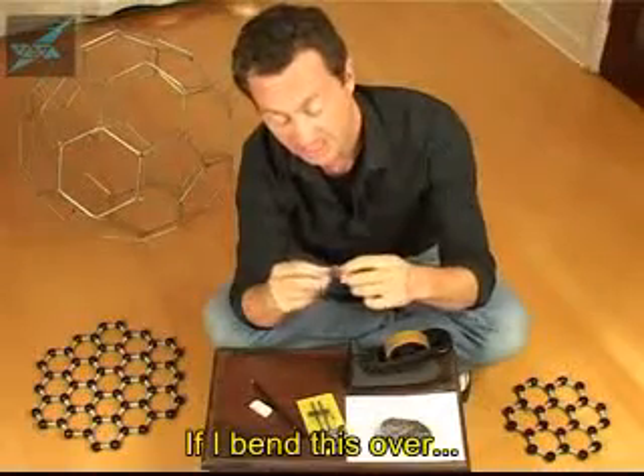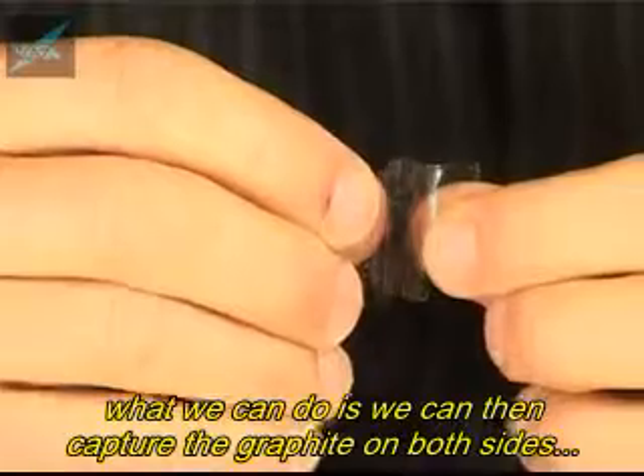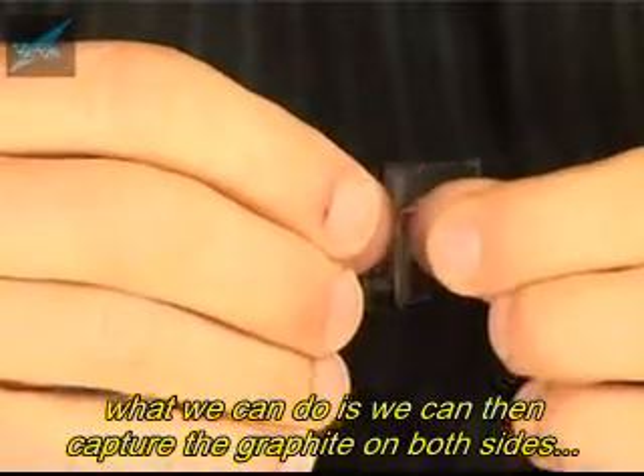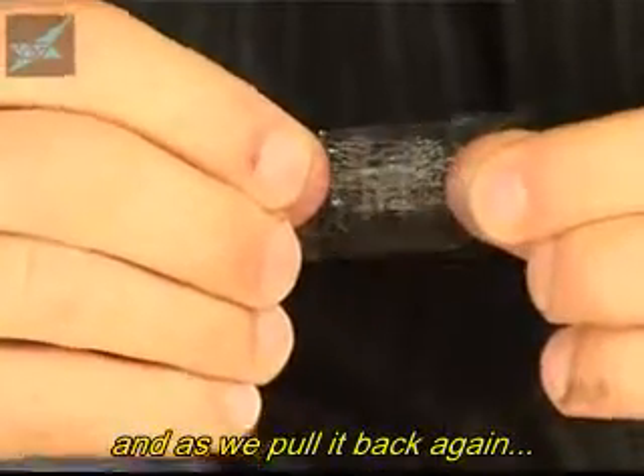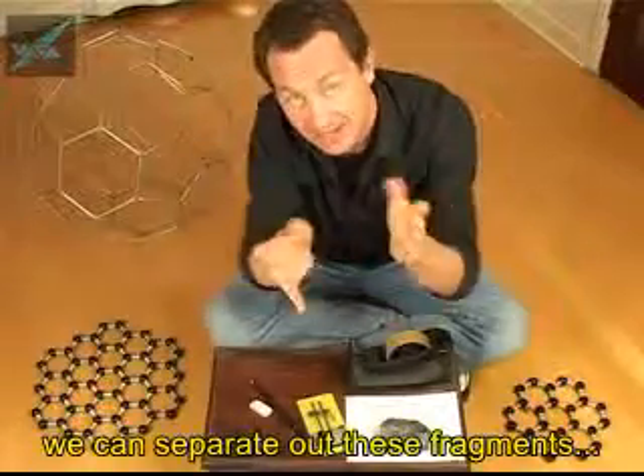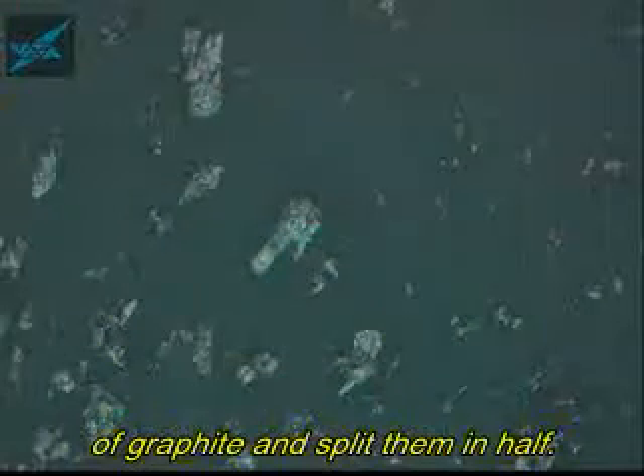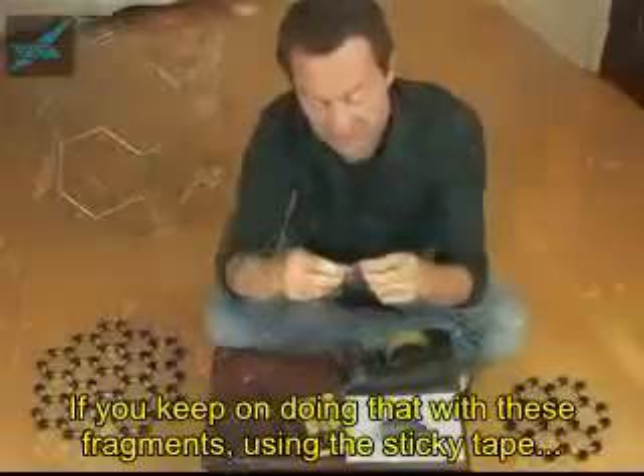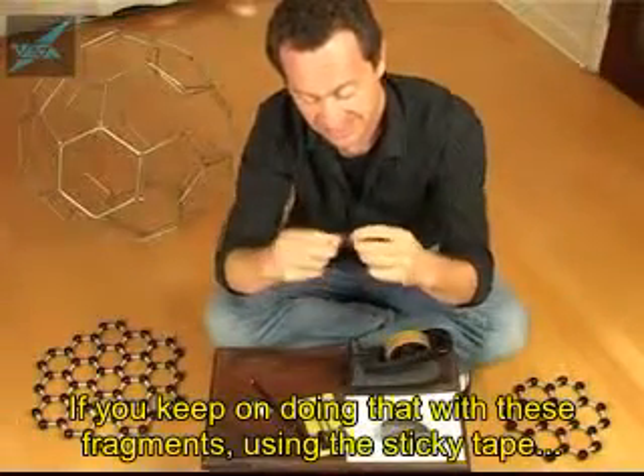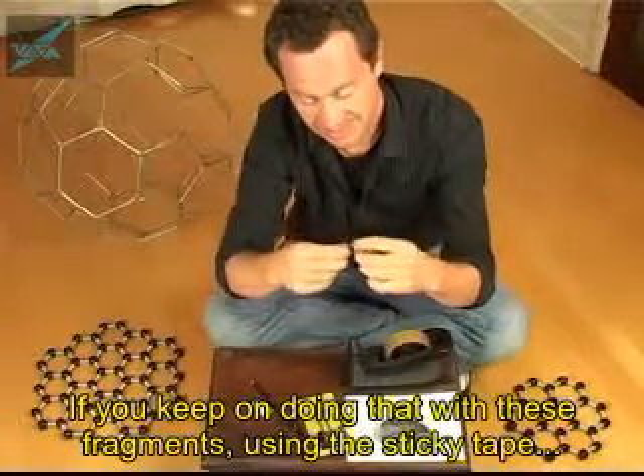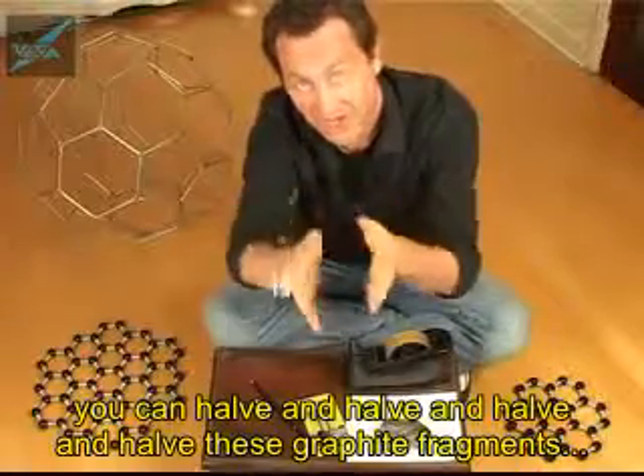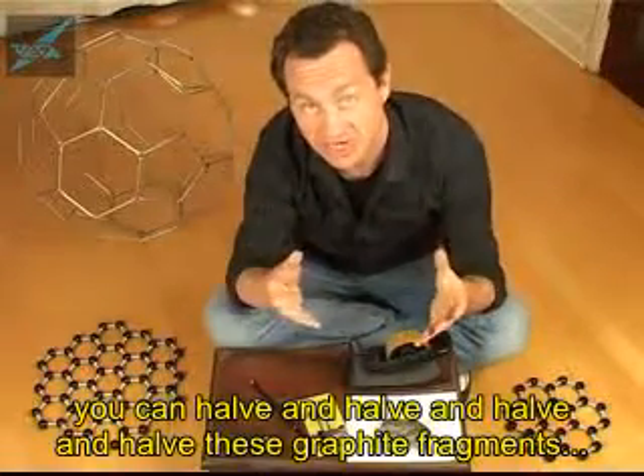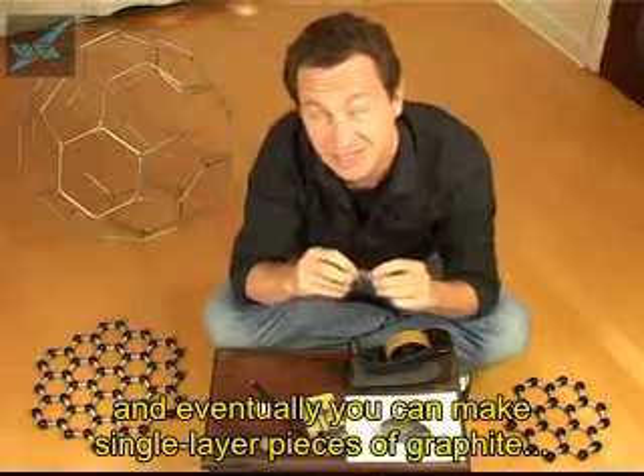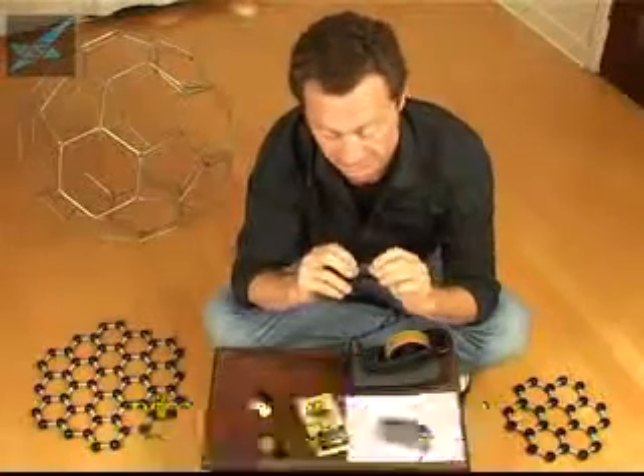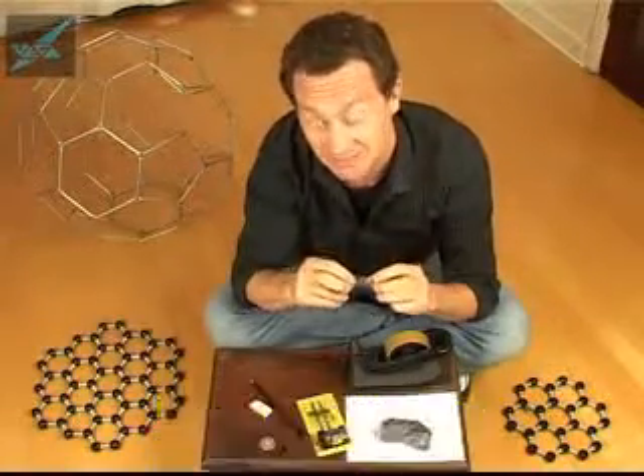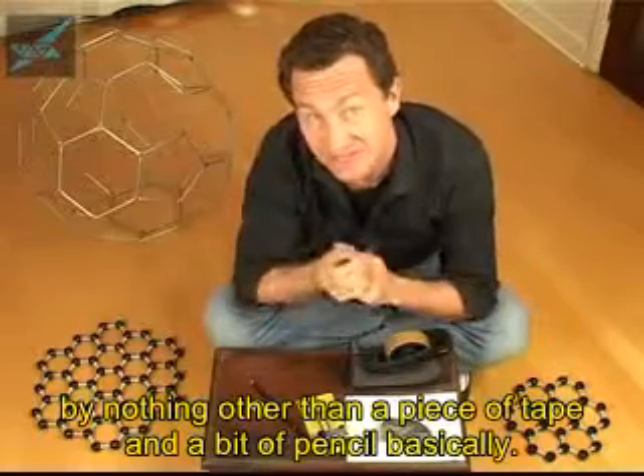Now if I bend this over, what we can do is we can then capture the graphite on both sides, and as we pull it back again, we can separate out these fragments of graphite and split them in half. And if we keep on doing that with these fragments, using the sticky tape, we can actually halve and halve and halve and halve these graphite fragments. And eventually you can make single layer pieces of graphite. In other words, you can make graphene sheets by nothing other than a piece of tape and a bit of pencil, basically.